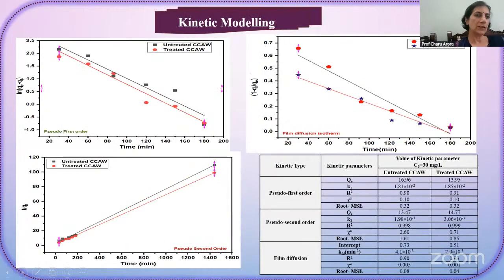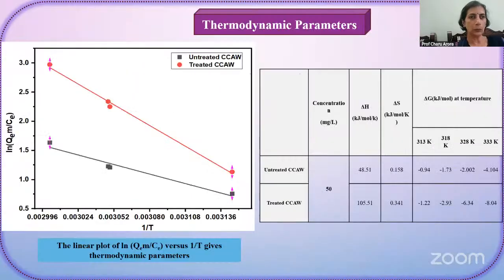Now, these are the plots for kinetic modeling: pseudo first order, pseudo second order, and film diffusion model. Again, you can see that the value of R square is maximum for pseudo second order, which means it is the best fit for the removal process. And thermodynamic parameters for both the adsorbents were also calculated and reported in this table.